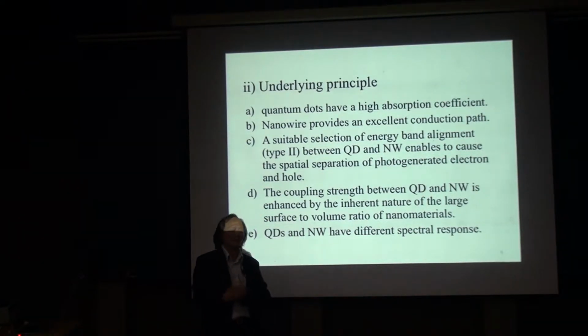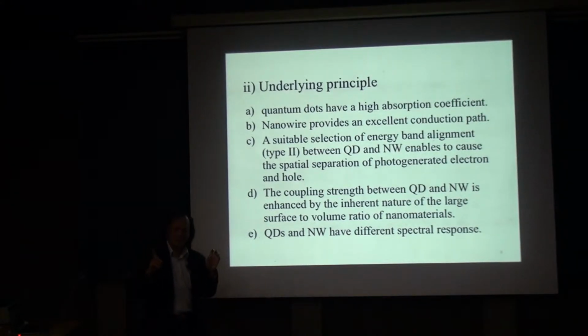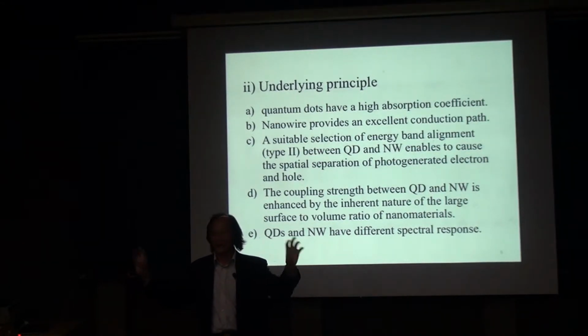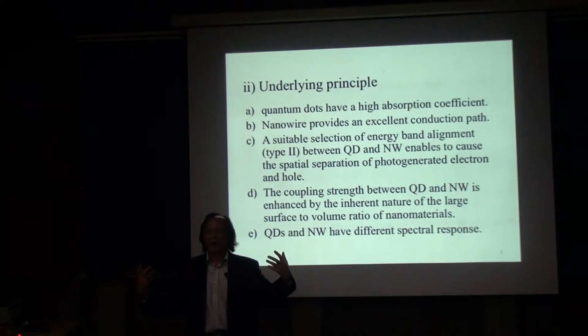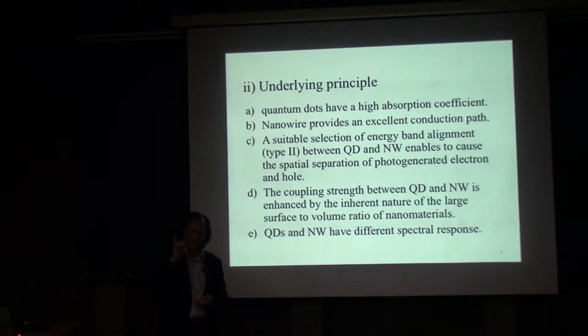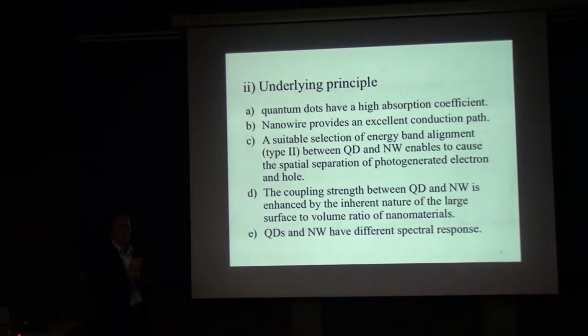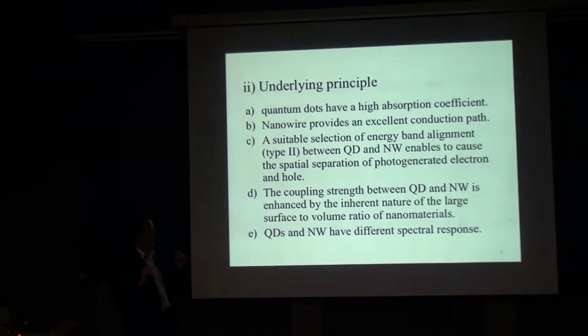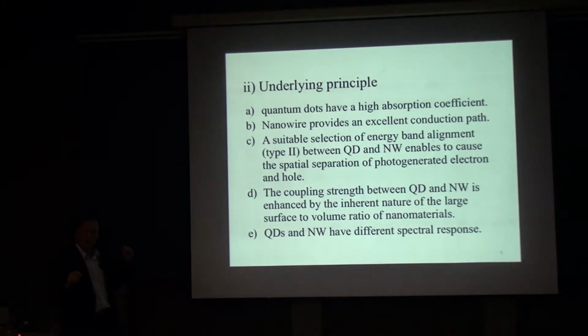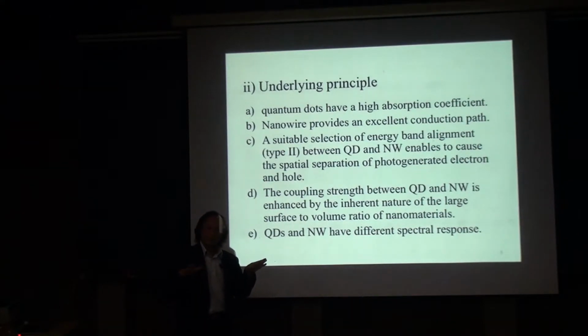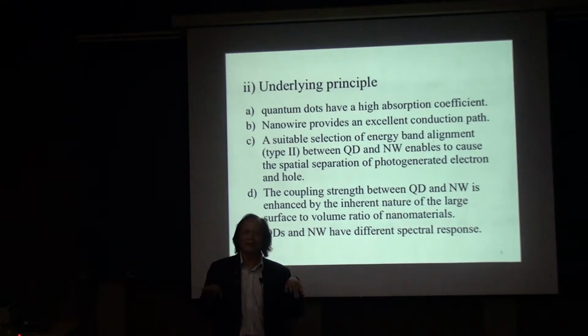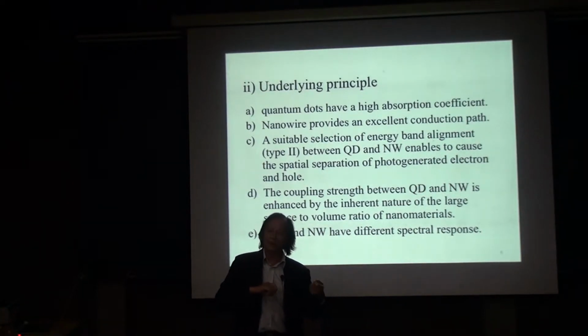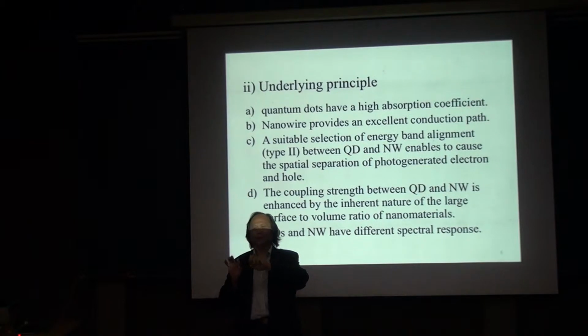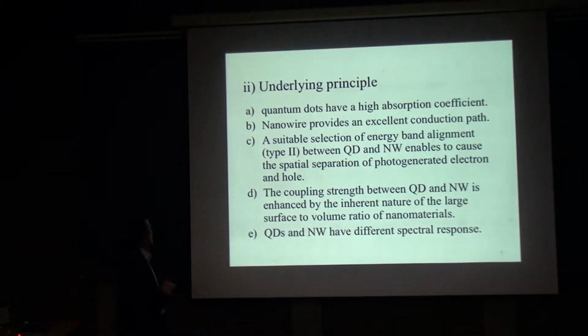That's the key point. It is not just easy to say that putting one quantum dot and one nanowire together gives you a very good photodetector. No, there is a restriction, and this restriction is a key factor. You have to choose an appropriate band alignment, that's called the type II band alignment, between the quantum dot and the nanowire. Because of this particular band alignment, the excited electron or hole can jump into the nanowire and make the conduction. That's the key point.